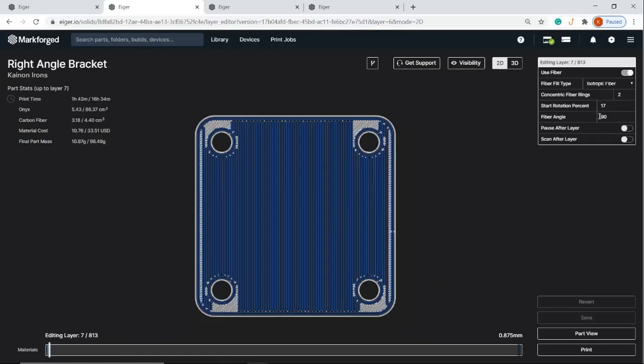Now, going back to why it's important to alternate these angles in certain cases, think about this angle here. So we're at 90 degrees, the fibers are facing vertically. What if we were to reinforce this part completely with these 90-degree panels? Think about loading conditions. And so if we bent the part along a vertical axis, those fibers wouldn't be placed in tension. And so you wouldn't be getting the most out of the system. And so that's why it's important in many cases to alternate.